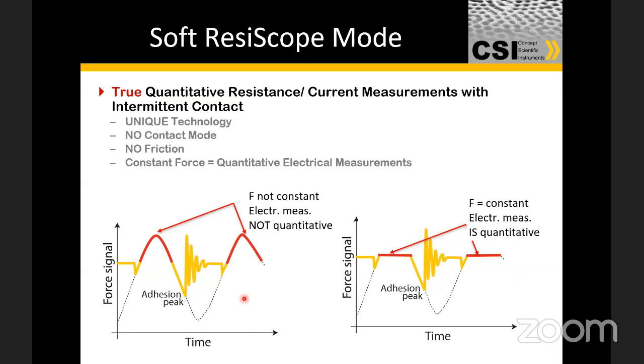And obviously, what that allows us to do is get over some of the classical tip sample interaction problems that we are likely to face, because of adhesion between the tip and the sample. As we know that organic surfaces are always a lot stickier, so the adhesion is higher. And in classic measurement techniques, this can lead to a lower resolution on the functional measurements, like current, that we're trying to do here. So this is how the intermittent contact allows us to circumvent this problem.